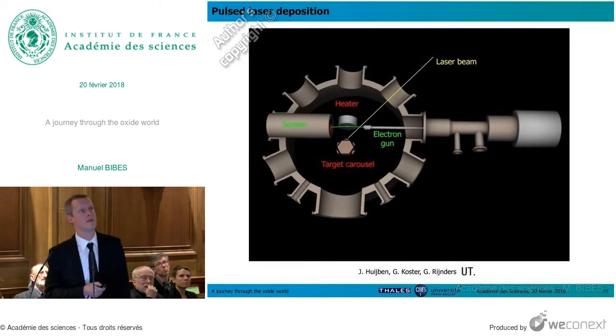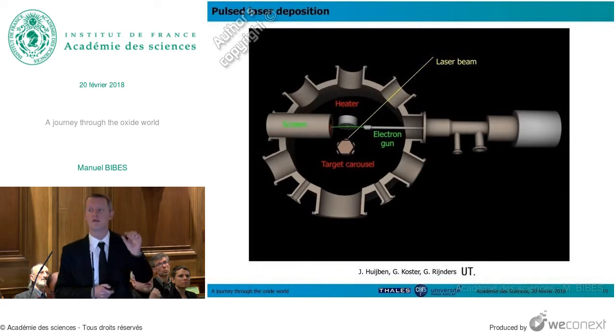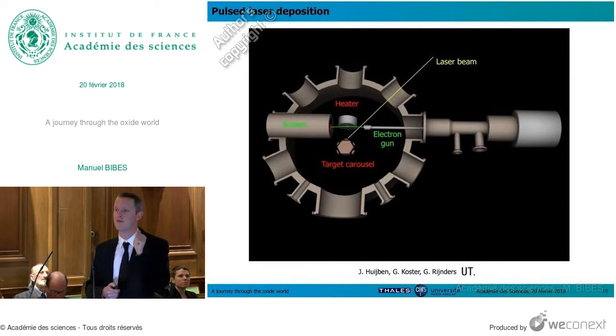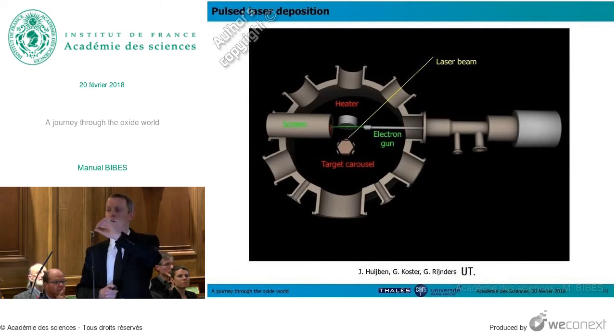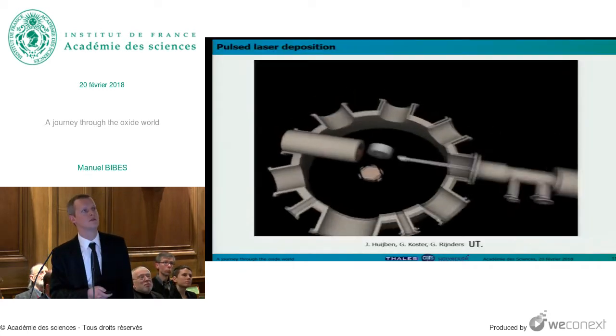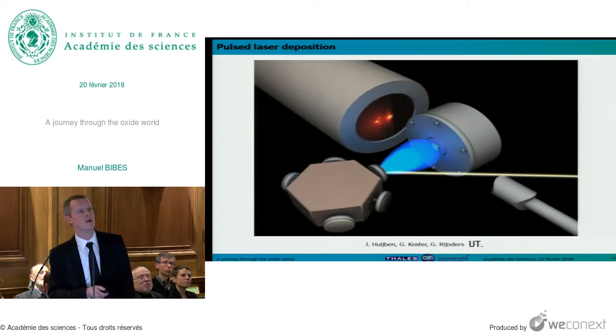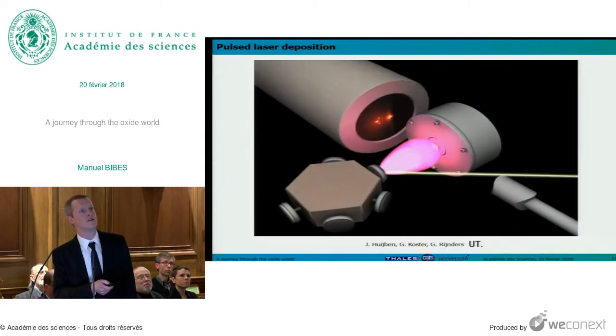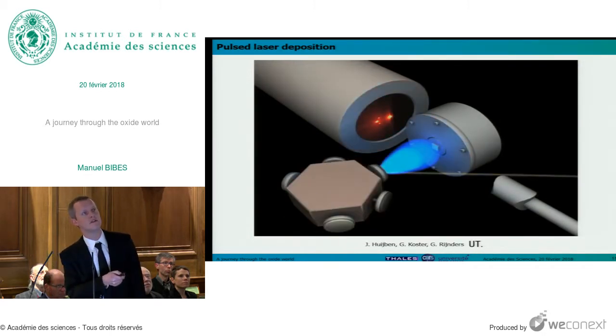It contains all the elements which we want to have in the thin film we are going to deposit. In front of the target, we have a small piece of crystal, which we call the substrate. And we are going to deposit a very thin layer of the material of the target, layer by layer, so atomic layer by atomic layer. I have a small animation for you to understand this a little better. This is again from my colleagues from Twente. You see that the laser is coming, hitting the target, and this evaporates the material, which is then deposited on the substrate.